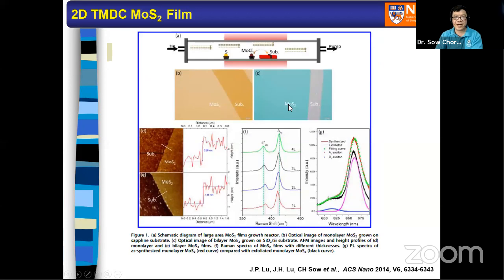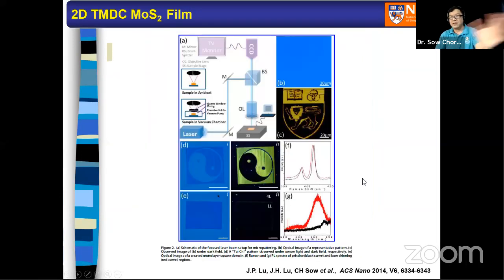So for example, here is our MoS2. It's so nicely grown, you cannot see it. So we use a pen knife to make some scratch so that you can see that there's nothing there, then MoS2. And we do the characterizations. AFM measures it's one monolayer in one case, and then let's say four layers in the other case. Raman tells you what happened. Fluorescence for multiple layers is not strong, monolayer very strong. And we can do laser patterning. Every student has their favorite pattern.